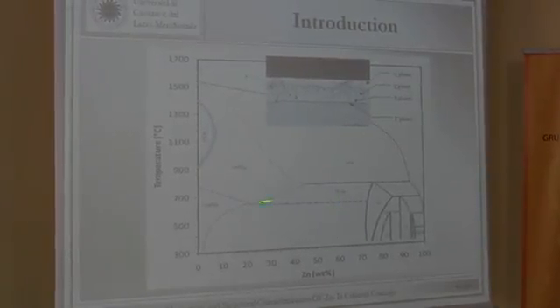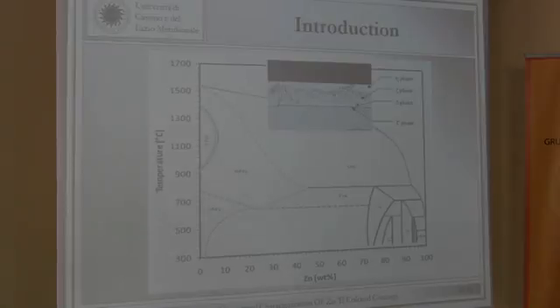of zinc. Sometimes it is named with the capital gamma letter. Then we have a delta phase in this concentration, corresponding to this thin coating. Zeta phase, characterized by columnar morphology. It's a very funny phase because it's very simple to discover. And then we have in the outer zone the presence of eta phase. The chemical composition of eta phase is quite similar to the composition of the bath, but it is due to wettability of metal on the surface. The presence of this phase is due not so much to an interdiffusion phenomenon.